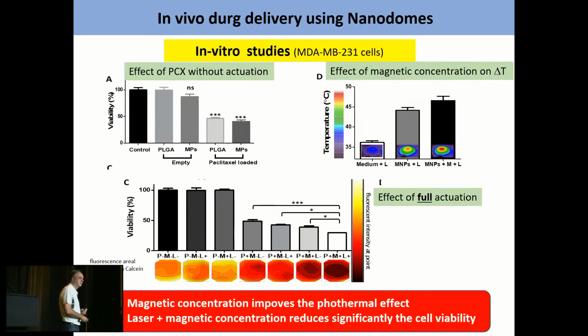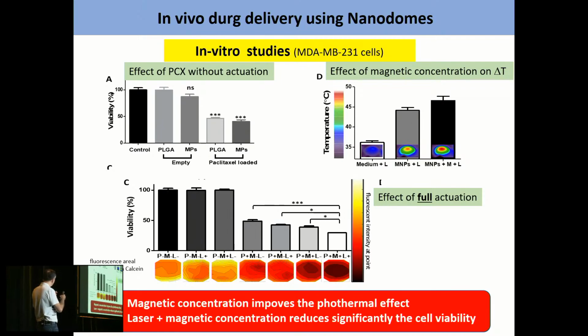So first, what we did in the in vitro studies is to check the effect of the drug. First, we check the cell viability using only the PLGA beads, with nothing inside, or without the nanodomes, and there is no change. When we use the nanodomes, there's a slight change, but there's no statistical significance. When we use the PLGA bead with the drugs, it does have a reduction of cells, meaning that the drug works even if it's inside the PLGA. And the same, when we do the full nanodomes with the shell, the drug, and the PLGA, the drug still works and kills the cells.